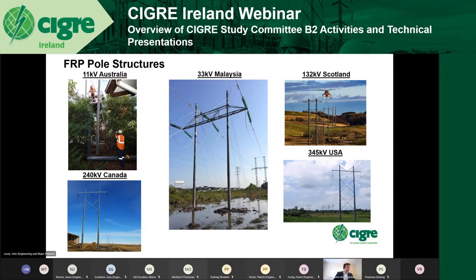240 kV in Canada. You probably can just make out in the background the steel lattice towers. I think in this case, the reason why the composites were actually put in that location is to reduce the footprint of the structure. And the last example here, 345 at the upper end, just an example, and you can actually see that they're starting to use more and more cross bracing, obviously, because the loading is starting to increase.